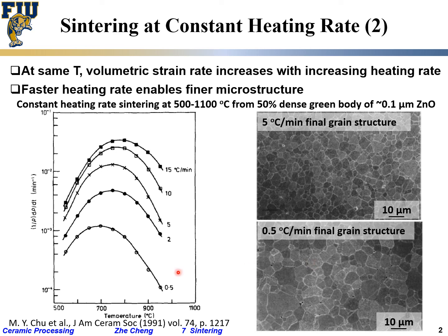As long as the relative density is the same, faster heating gives better hardness and toughness. That is why people often try to use higher heating rates. However, you are limited by your furnace capability, your heating rate capacity, and your sample size. You are also concerned with thermal stress — heating too fast may cause cracking. So it is still a compromise: generally you want a faster heating rate for finer microstructure and better mechanical properties, but it is not simply the higher the better.